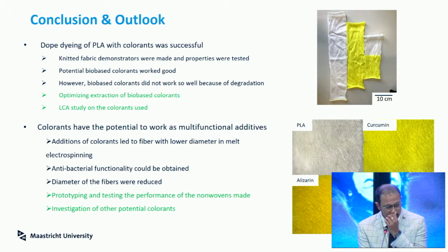And as the second outcome for the electrospinning, the colorants actually have a potential to work as multifunctional additive, and addition of these colorants actually led to the effect we were hoping for. We had lower diameter and also antibacterial functionality. Of course, it has not been tested against a variety of bacteria and viruses and so on, but this is already quite a nice step in a really nice direction. And so, of course, the next step for this as a follow-up would be to prototype and test the performance of these non-wovens that were made, and also investigation of other colorants or additives that could be used for such antibacterial applications.